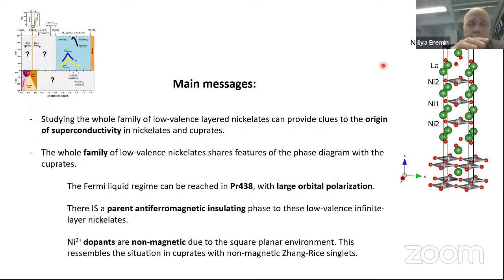Am I correct? Somehow I have a feeling that when you were showing the lanthanum nickel O2 band structure, I guess this was computed for the structural parameters of the bulk. How would this band structure change if you do it on the STO? Because somehow I understand that the lattice parameter, if you grow it on the STO, is a bit different. And my impression, I mean, again, I did not put two pictures next to each other, but somehow I had the feeling that they are not identical to some extent, especially with respect to the x squared minus y squared band. Somehow it looks like it becomes more flat. Is the lattice constant in the plane also extended?